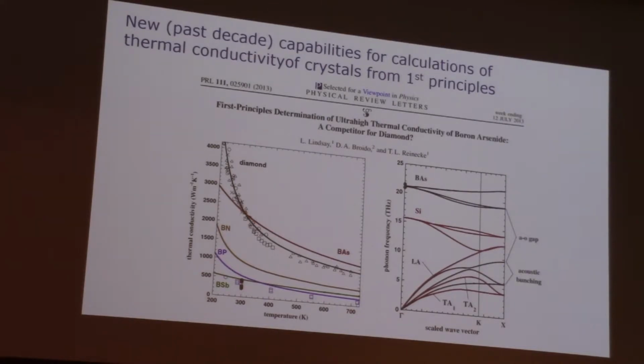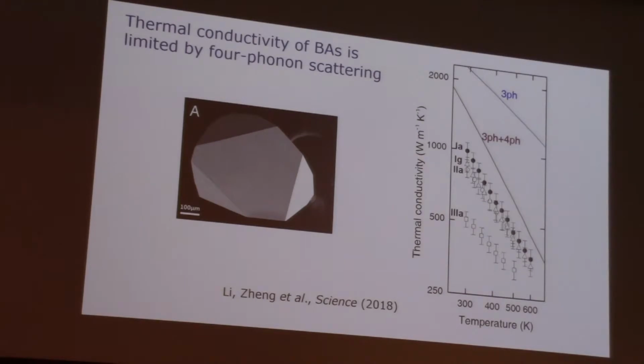Got a lot of people excited, got federal agencies writing checks. And so there was a MURI formed, this multidisciplinary university research initiative group, got together and grew crystals and worked hard to make them better and better, do measurements, and then this was kind of the ultimate. This is the paper from my group. That's my student, Chia Zhang, in Science. And so what we found is that the best crystals have a thermal conductivity of about 1,000 watt per meter Kelvin at room temperature.